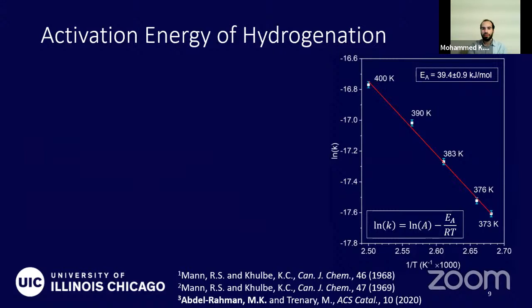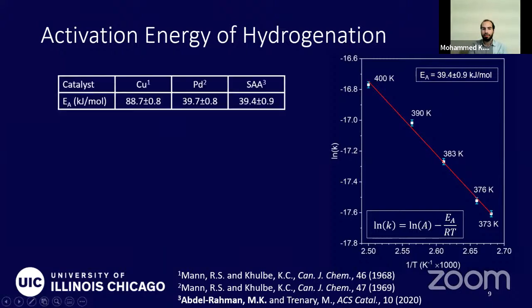And so to go one step further, we varied the temperature and we determined the activation energy of the reaction by using a simple Van 't Hoff plot. And from here, we again compared to the Mann and Khulbe work from the 60s, and we find that the activation energy is also the same as a pure palladium catalyst.